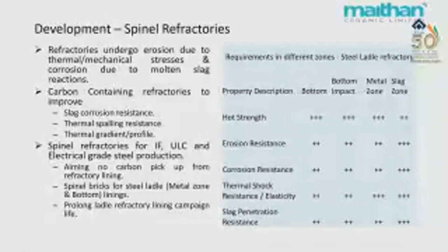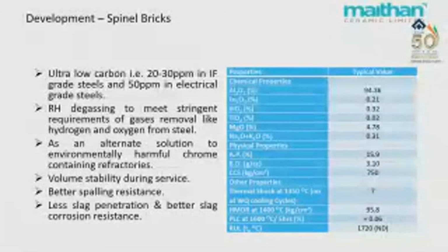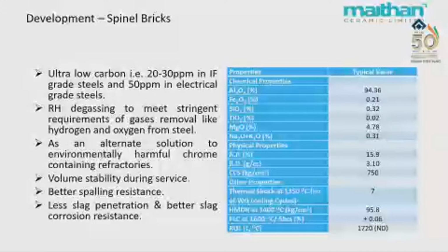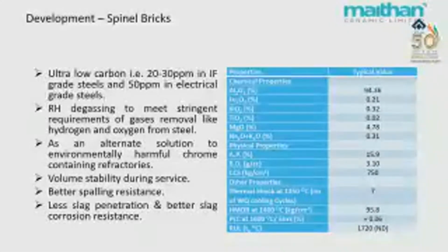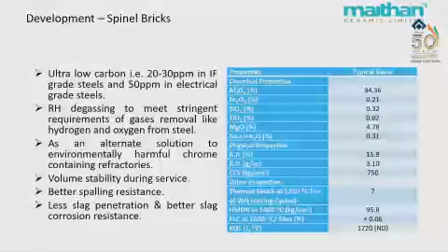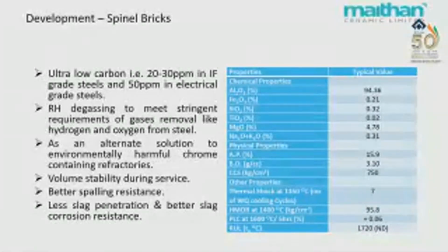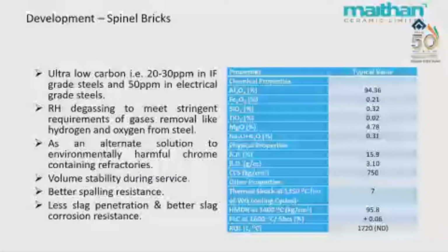So basically the spinel refractories are replacing magnesia carbon refractories for steel ladles, and we are aiming at ultra low carbon steel grades, because for IF steel the requirement of carbon is 20 to 30 ppm, where even a couple of ppm matters. So hence this is the requirement of no carbon or carbon free refractories like spinel. Then the RH degassing, mainly these are designed for the bottom.